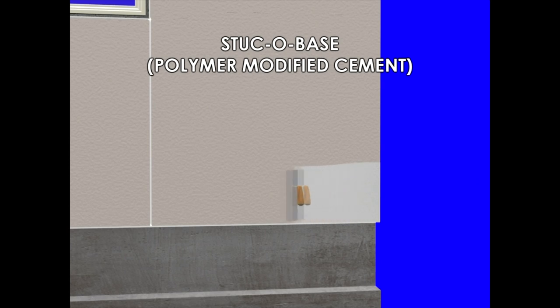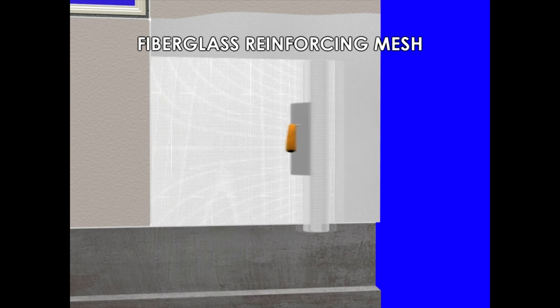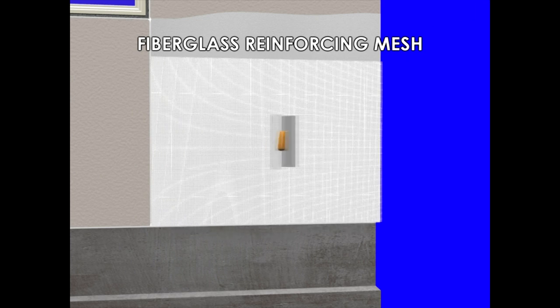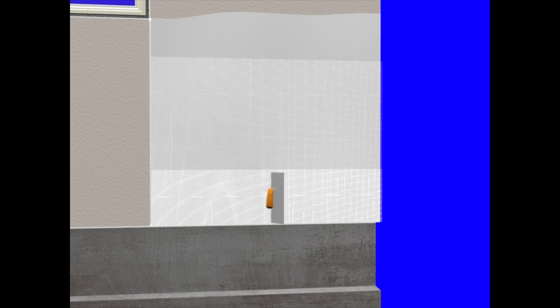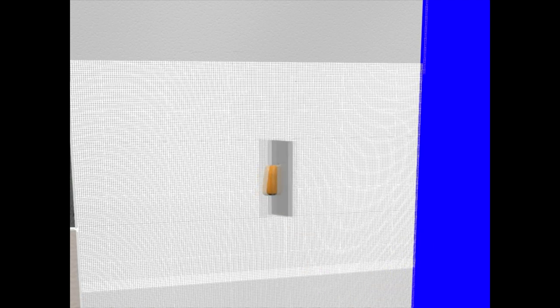Now we're ready for the stucco base, the polymer modified cement, and the fiberglass reinforcing mesh. This step provides a multitude of benefits. It reduces the likelihood of efflorescence, the white powder we see from time to time on stucco jobs. It also creates a uniform porosity or suction across the wall. This is very advantageous to the appearance of the finish coat once it's installed. It also creates a much smoother wall surface, certainly important in larger jobs and also in critical light conditions. But most importantly, this step will reduce the likelihood of cracks. The combination of fiberglass reinforcing mesh and polymer modified cement helps to distribute the stresses and prevent cracking. It also strengthens that exterior surface of the brown coat.